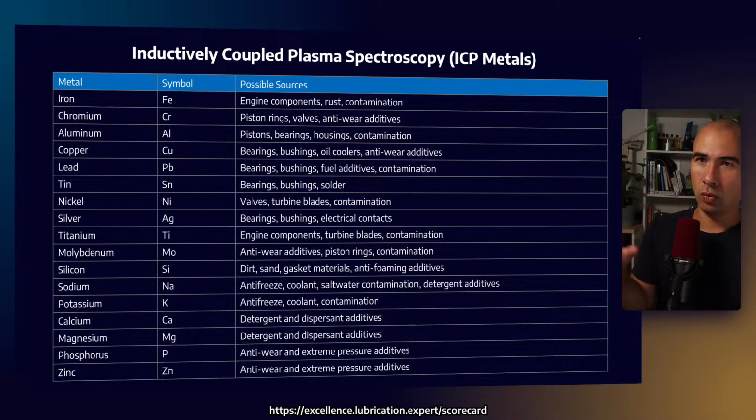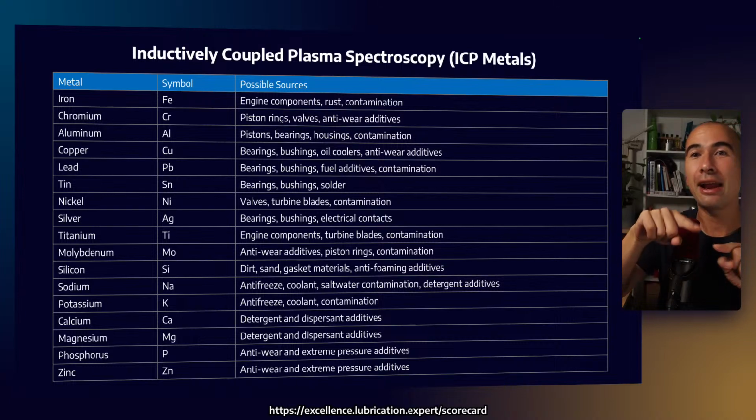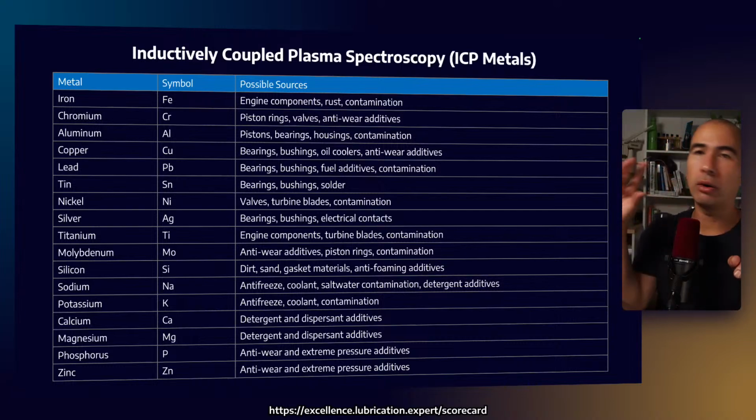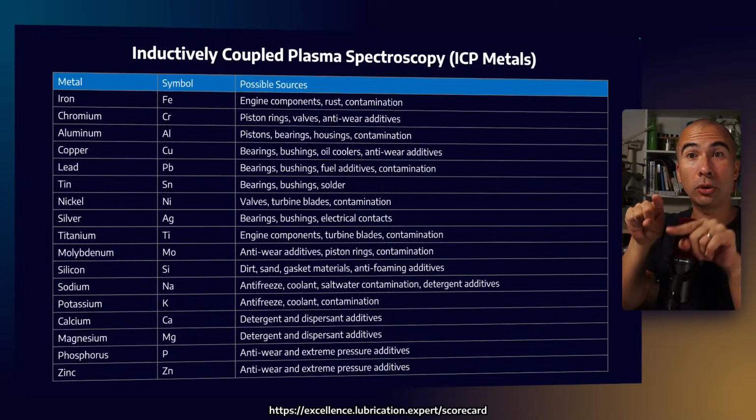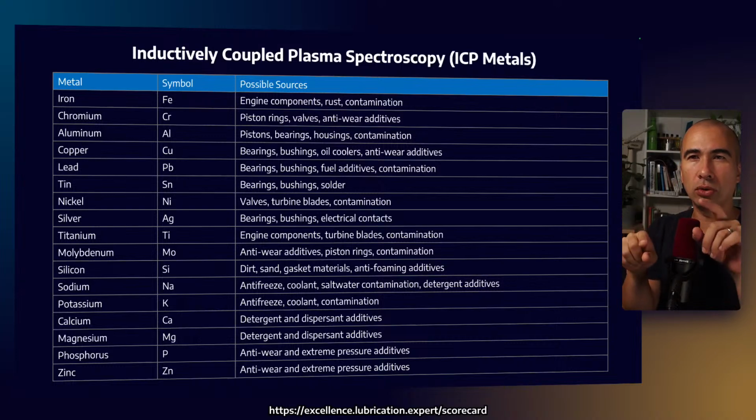Now, one thing is that when you have dust ingress or dirt ingress, most of the time, most dirt is not silicon alone. It's usually a combination of silicon and aluminium. Now, wherever you are in the world, the proportions of those will vary anywhere between 2 to 1 and I think about 12 to 1.